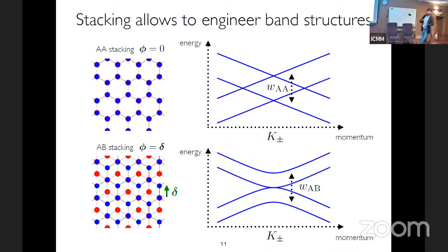By stacking, I mean the vertical atomic arrangement of the two layers that is going to modify the band structure. The way I'm going to parameterize different stacking configurations is in terms of a two-dimensional vector. My reference in configuration space is what I'm going to call AA stacking. That corresponds to this configuration, where atoms in the same sublattice in both layers lie on top of each other. By shifting one layer, let's say the top layer, with respect to the bottom layer by a vector equal to a nearest neighbor vector, for example, that produces AB stacking or Bernal stacking, which is actually the minimum energy configuration.